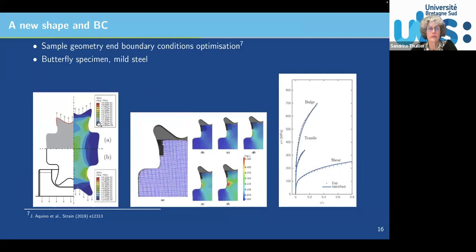Another example that I've maybe already mentioned a little previously is this shape, which was designed by shape optimization. So we used an indicator in order to promote several features, to enhance heterogeneity, to enhance several strain modes over the sample. And the funny shape that you have here comes from this shape optimization. So this is numerical simulation. This is a real experiment. And you have, again, a comparison of several tests. We performed the test in shear, tension, and hydraulic bulging, but we also did the simulation with the parameters identified from this test, and you have a really good agreement. In this case, it was also hardening and anisotropy. It's just to illustrate that it's a different shape, but it can still give you a good answer.